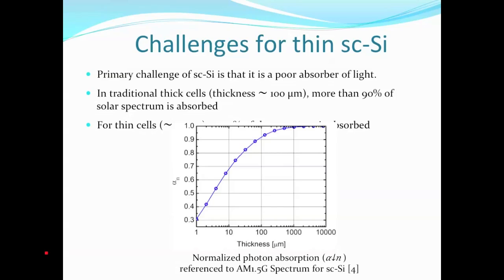When we drop the thickness by an order of magnitude, we lose some absorption. So the absorption, by dropping it by a factor of 10 down to 10 microns of thickness, we end up getting about 68% in absorption. So it's not terrible. Even at 10 microns of thickness, since silicon's still absorbing quite a bit, we could probably achieve a decent cell performance from this thickness. But we do want to make up for the absorption losses, so we need to implement some kind of scheme to enhance absorption.